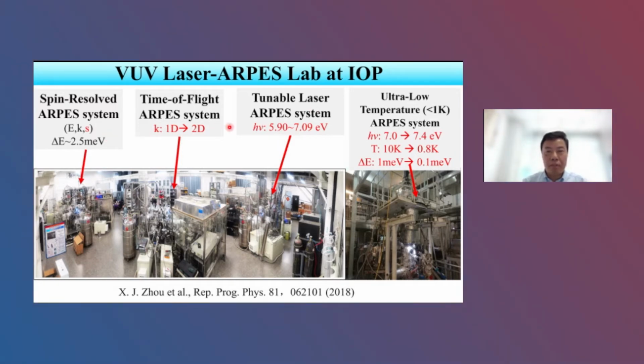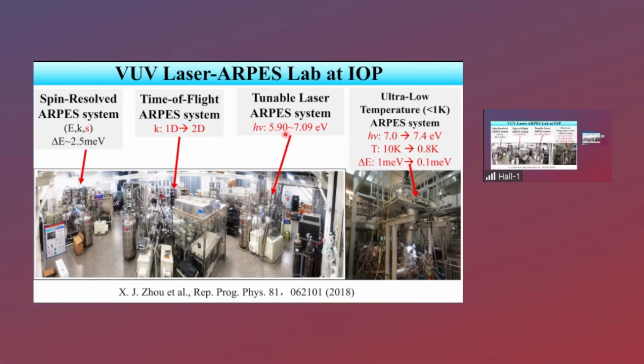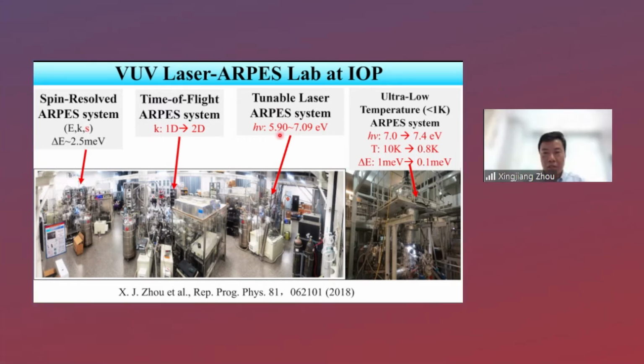At the beginning, we developed the laser ARPES. Then we upgraded the laser ARPES by using a tunable laser, which can tune the photon energy between 5.9 and 7.1 eV. The second one is the spin-resolved ARPES. By using spin-resolved ARPES with a UV laser, we can greatly improve the energy resolution. Actually, we can achieve 2.5 meV resolution. That's really one of the best in the world in spin-resolved ARPES.